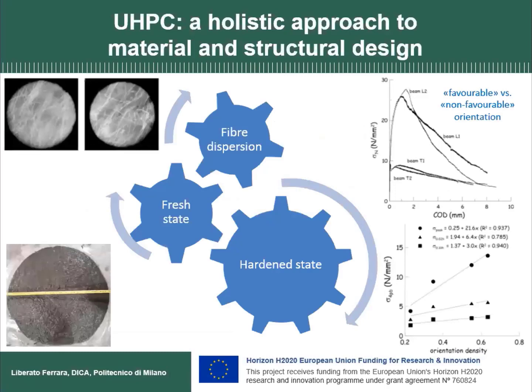We have also learned from previous presentations how in UHPC, fresh state performance and rheology, fiber dispersion, hardened state performance, and then structural performance are strictly correlated with a mutual interaction. On the right-hand side of this slide are some results we obtained about 10 years ago, in which, controlling the orientation of the fibers, with exactly the same material and the same structure, simply testing it in one direction rather than the other, you get a very different performance at the material and structural level.